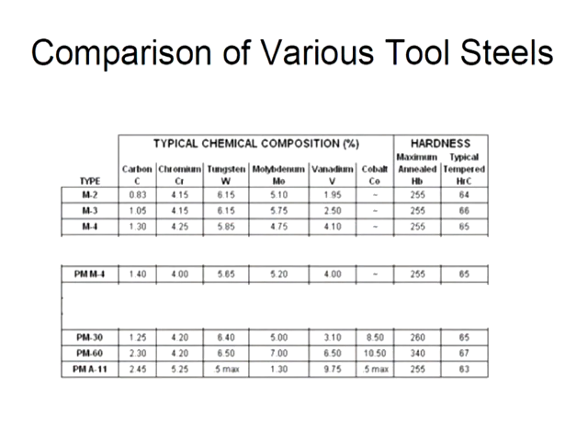Okay, here's another one. Some of your common ones here you'll see, the top ones, your M2, 3, and 4. See, the vanadium is a common alloy. Here's your tungsten. Tungsten's very high. Your chrome. Like I said, the carbon with the chrome, tungsten, and vanadium form carbides. Carbides are very small, very hard particles, and that's what gives you your wear resistance. Here you can see the hardnesses of those, 64, 66, 65, very hard.